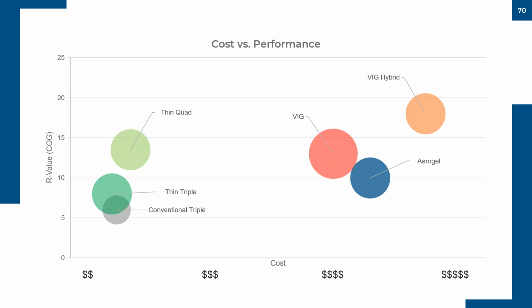So to recap, in comparison, there's several different factors. Really what we're looking for are solutions that are available today to meet many of the energy code standards that are coming online today as we reach towards electrification and affordability. And so here's a small snapshot of where conventional triple pane glass is as far as cost standpoint and overall center of glass performance values, just about ranging between R5, a little bit lower than R10. Your thin triples have a little bit higher range than conventional triples. That's due in large part to the seals and the gas fills that are being used with thin triples. And then your thin quads have a higher range, slightly higher price point along with that too.